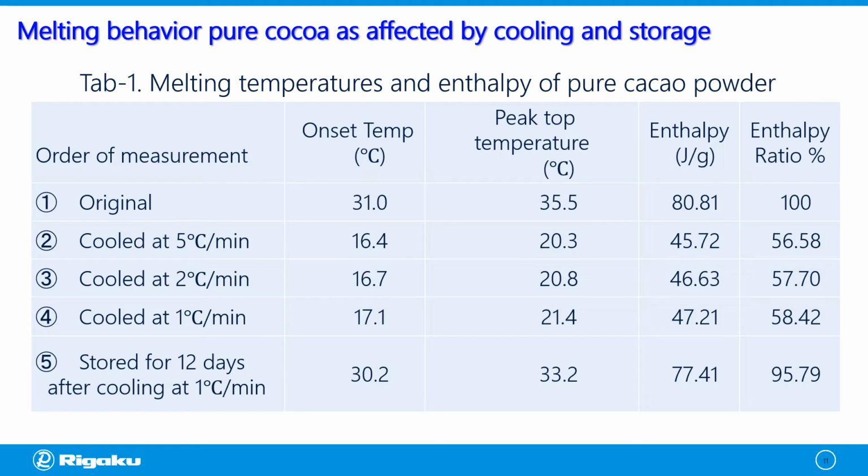The melting energy or enthalpy of the sample with different cooling rates are approximately 60% compared to the fresh or original sample's melting energy. On the other hand, storing the sample for 12 days has increased the melting enthalpy ratio to 96%.